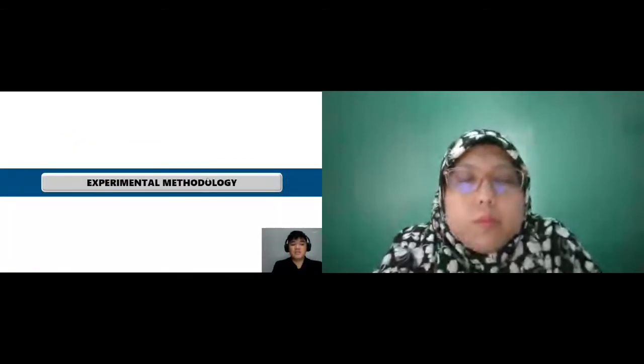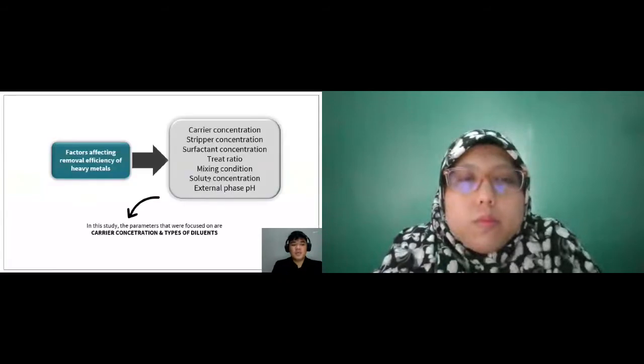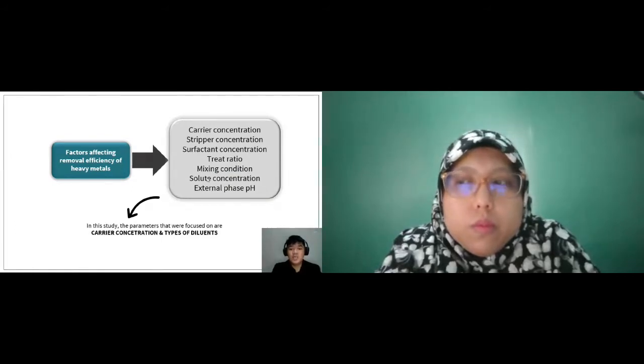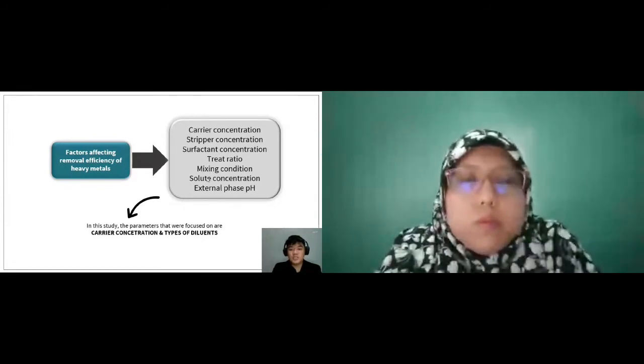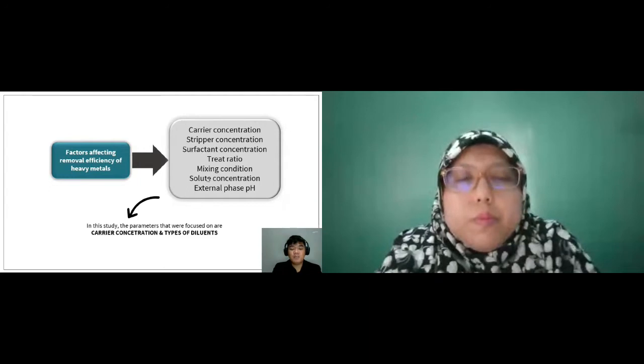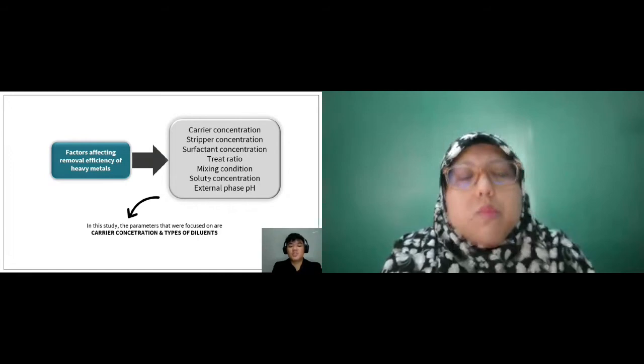Next is the experimental methodology. It is crucial to identify optimal process parameters involved in emulsion liquid membrane in order to achieve membrane stability and to obtain highest extraction and stripping of metal ions. Some of the parameters are carrier concentration, stripper concentration, surfactant concentration, treat ratio, mixing condition, solute concentration, and the pH of the external phase. In this work, carrier concentration and types of diluent used were the parameters that were varied, while the other parameters were kept constant to observe the effect on the removal of heavy metal ions.